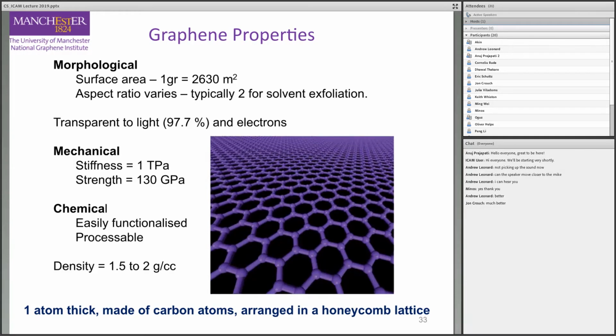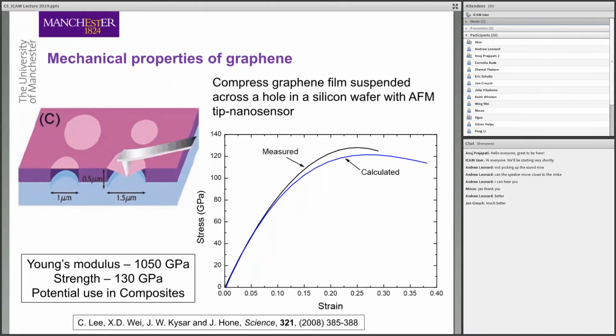And of course, always the question is how you can measure those properties, how you can achieve those properties. And here we can see a graphene platelet where we test it with the atomic force microscope with a nanosensor at its tip, and we derive the stress-strain response and measure the Young's modulus of over 1 terapascal with a strength of 130 gigapascals.